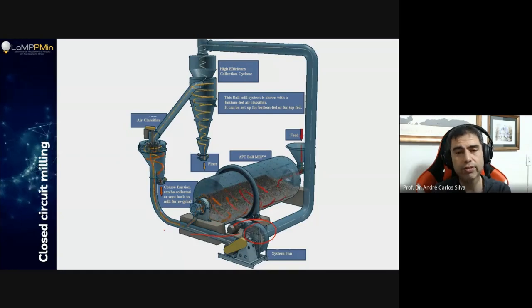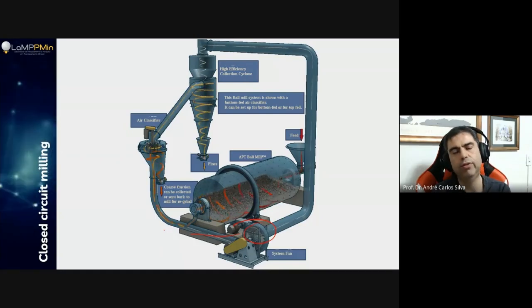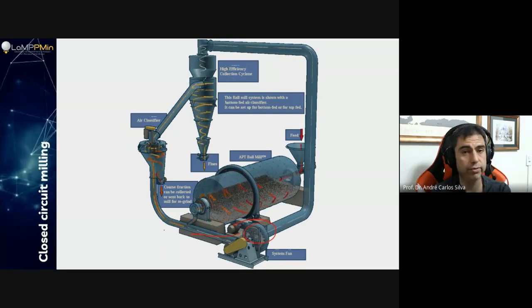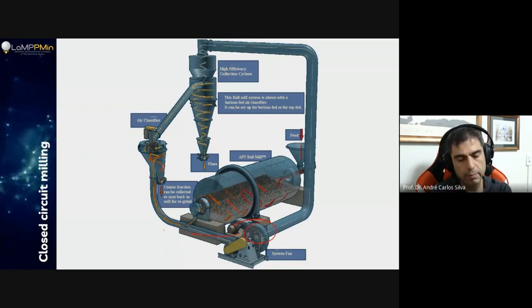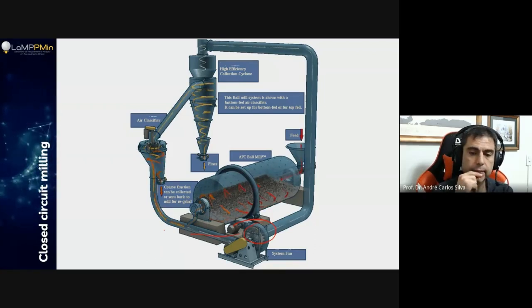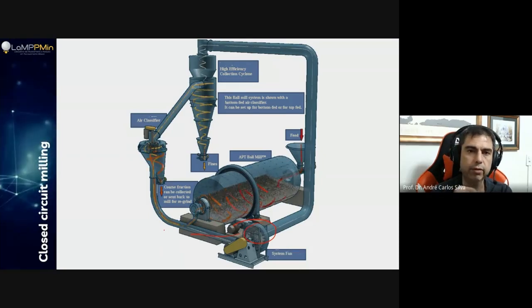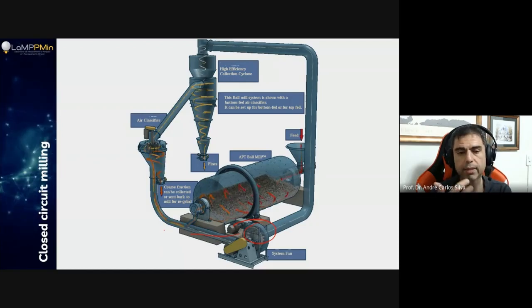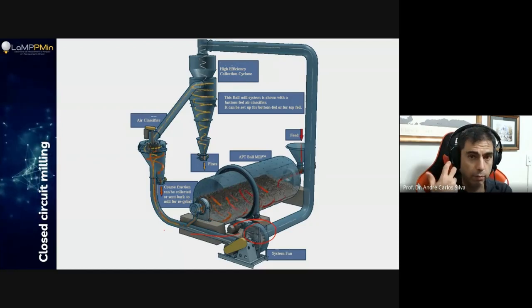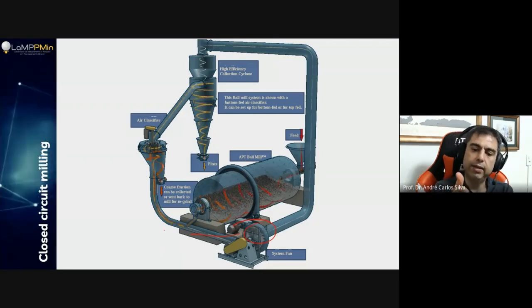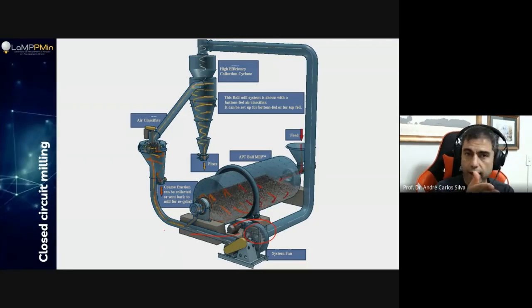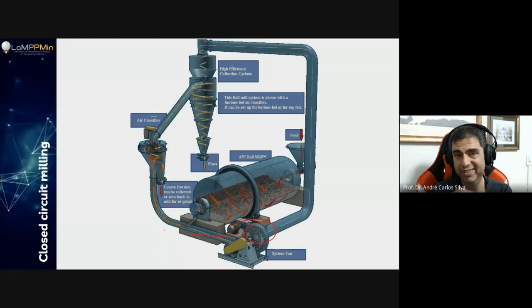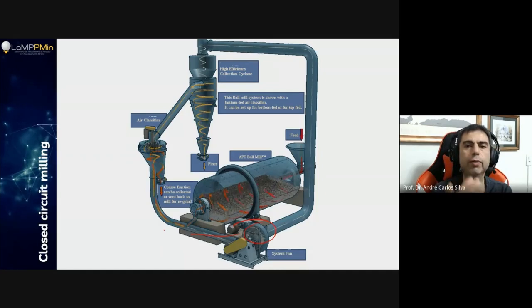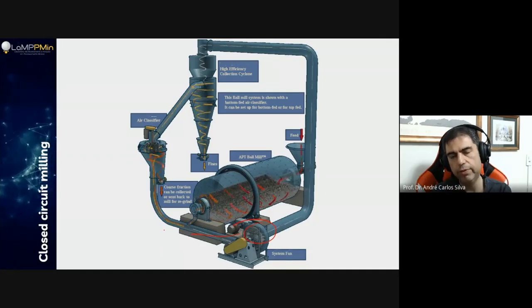If we add water to this, it would be almost the standard closed circuit that we use around the world, okay? So this is standard. Many companies use the same technology. It works quite well. And when I mentioned to you before that we have a circulating load in Catalão around 600%, and I know it's surprising, but now you can understand this better. It's easy for us to have the material go into the mill, stay a small amount of material over there, so the residence time would be very short, and then we check whether the material agrees with our standard or not.